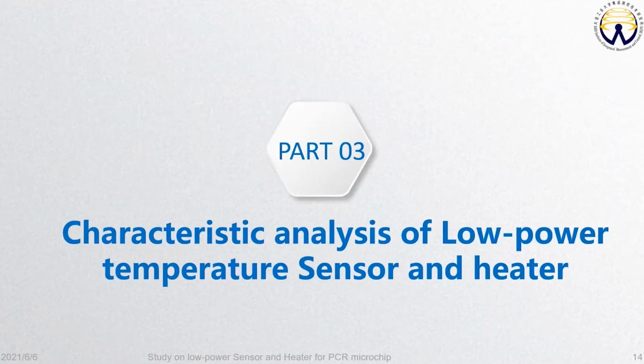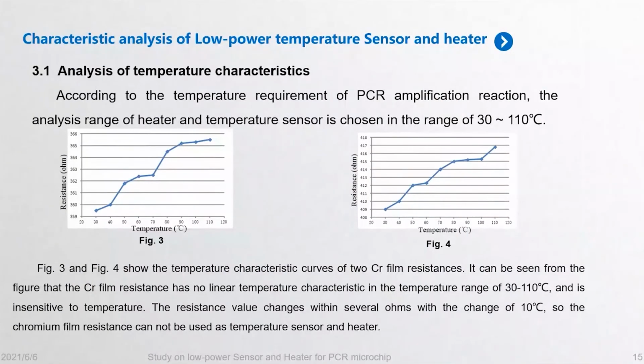Okay, now let's go to the third part of our presentation, the characteristic analysis of low power temperature sensor and heater. According to the temperature requirement of PCR amplification reaction, the analysis range of heater and temperature sensor is chosen in the range of 30 to 110 degrees centigrade. Figure 3 and Figure 4 show the temperature characteristic curves of two chromium film resistances. It can be seen that the chromium film resistance has no linear temperature characteristic and is insensitive to the temperature.